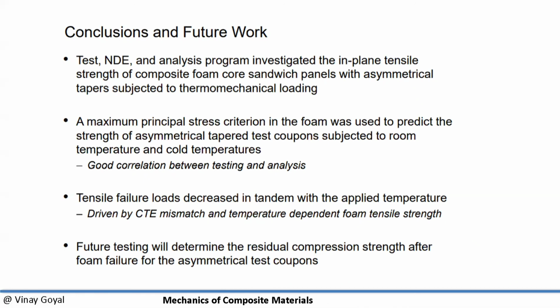Tensile failure loads were decreased due to the applied cold temperature, and that's driven by the coefficient of thermal expansion. The composite does not expand as much as aluminum, for example. So you have to consider that extra loading condition. And so what was very helpful was to divide the loading conditions as a function of time. So during manufacturing, we look at that. During temperature conditioning, we look at that. And when load is applied, we look at that. And so by adding all these things together, we can get a grander picture of what could be happening with this composite ramp in this example.